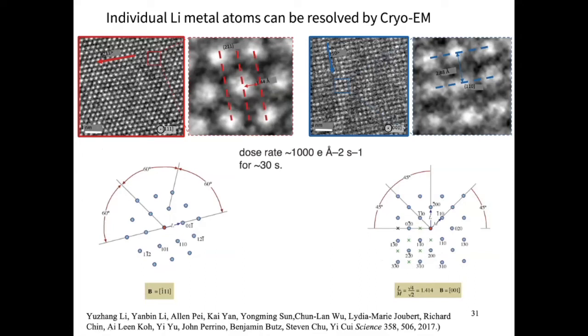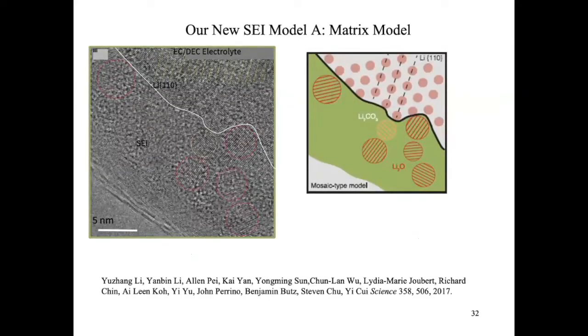In the past, even though some people showed some TEM images, I highly doubt that's real lithium metal, because lithium metal gets destroyed so fast by the e-beam. Now in the liquid nitrogen environment, we were able to resolve this. What's really important is that this offers a very powerful tool. Let's come to the interface.